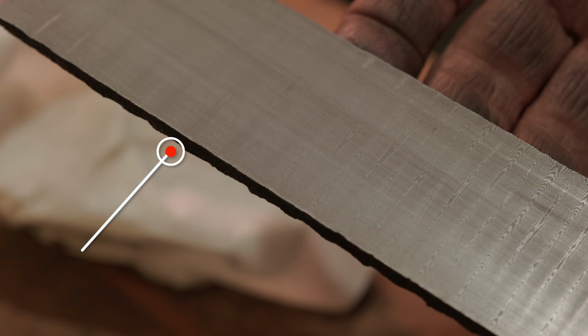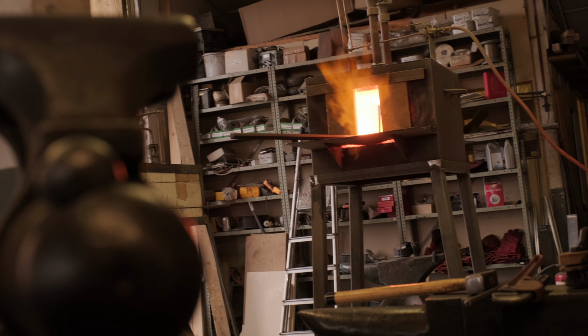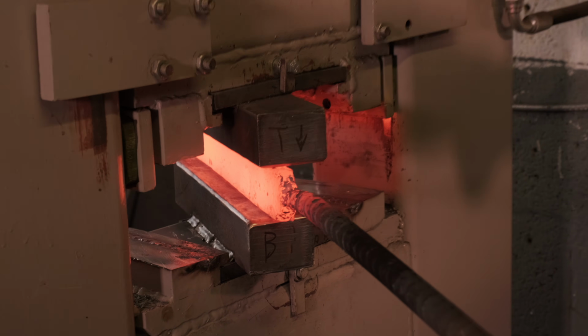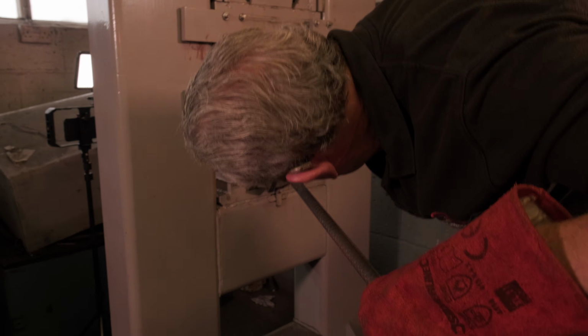are in your stack. Now, in order for that to happen, the surfaces need to be clean, free of muck and rubbish, at a high enough temperature that the crystals are going to grow very quickly, and under enough pressure that the surfaces are touching each other. So, first of all, if you're making up an original stack of Damascus, you've generally got nice clean sheets of steel. They're generally fairly flat.